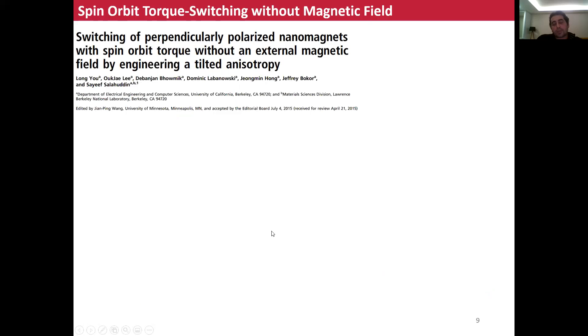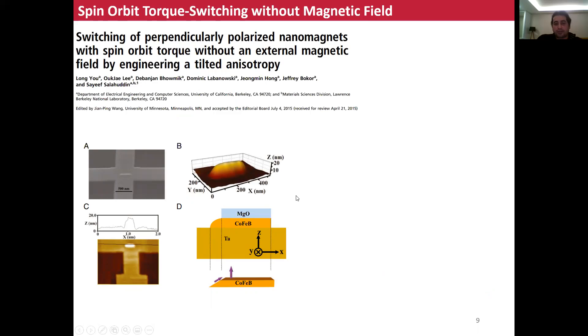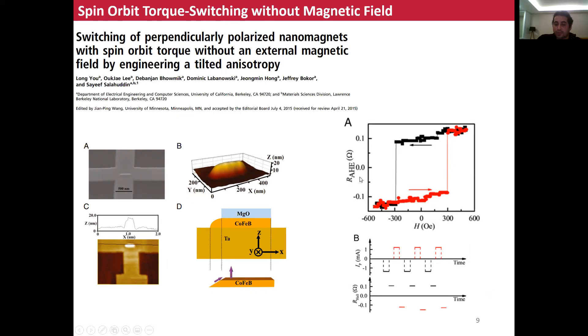In the literature, several studies have focused on removing the assisting magnetic field. In order to do this, they fabricate their structure in a wedge geometry. In addition to the perpendicular magnetic anisotropy, this wedge adds a tilted magnetic anisotropy to the system. They again characterized their sample using anomalous Hall resistance and observed characteristic switching under a magnetic field. Then they performed the experiment without any assisting magnetic field: when they applied minus one milliamp to the sample the resistance state was high, and when they applied positive one milliamp the resistance state was low. Without any external magnetic field, switching was successfully done using current.